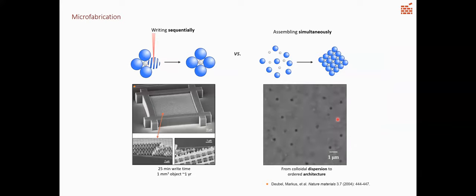And so how would we make such a material? And so immediately you might think, well, we can just directly write microstructure. I mean, you buy computer chips and their features are nanoscopic, not even microscopic. So the details that I'm talking about are more or less insignificant if you want to just generate something. But if we think about what if I want to make a large volume of this material, is that feasible? And so for instance, this is an example of basically a functional photonic crystal that has very well behaved photonic properties. And it takes about 25 minutes to write this little piece of material. And so if we extrapolate that to just a cubic millimeter, which is really the lower limit of what you consider macroscopic, it's going to take over a year of just writing with a laser in photoresist. And so it's really not feasible.